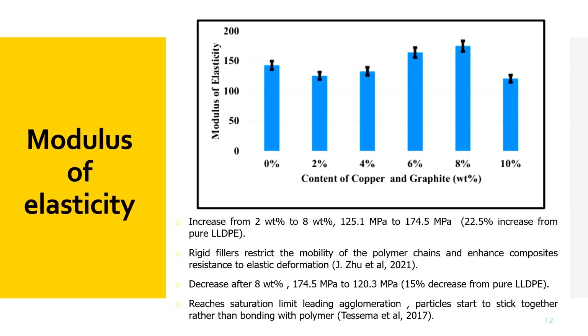So the decrease in the modulus might be due to some outlier of the sample, which might have agglomeration of particles or the hybrid fillers within the composite material.